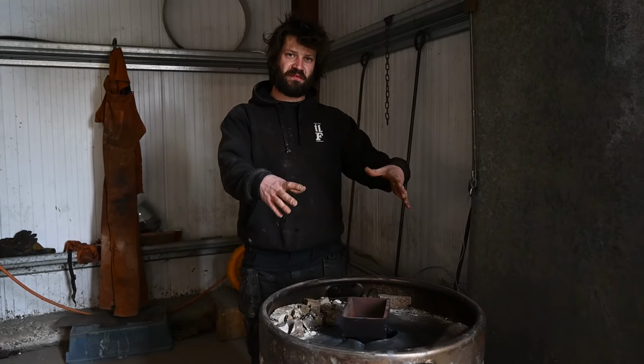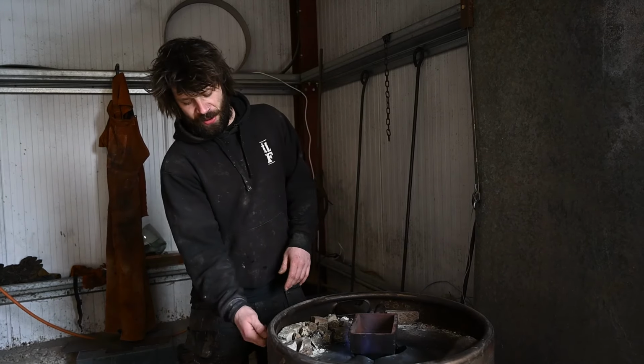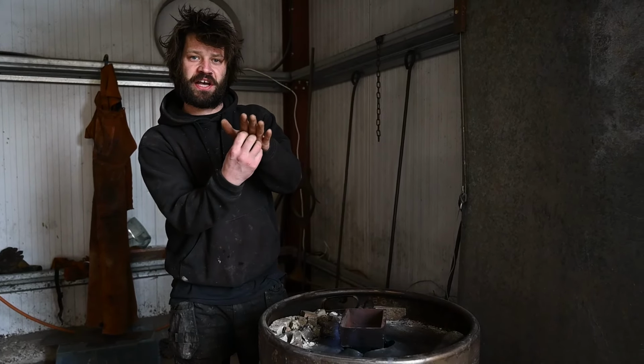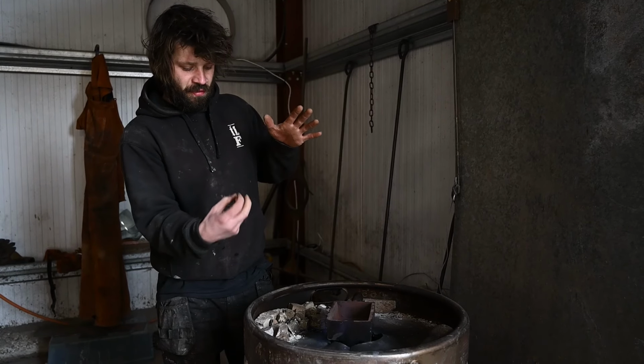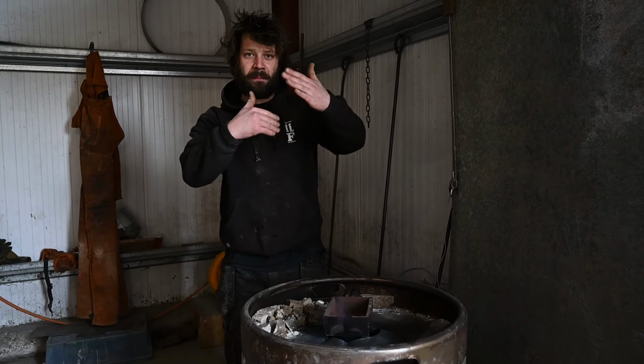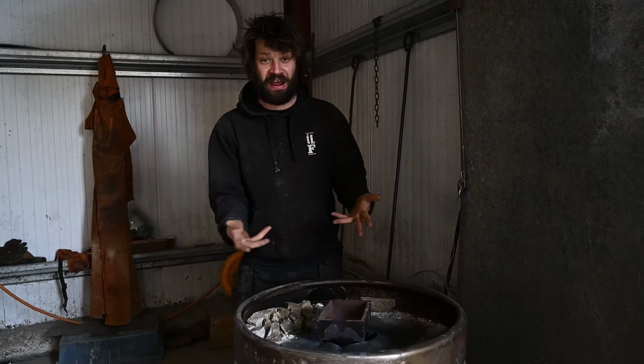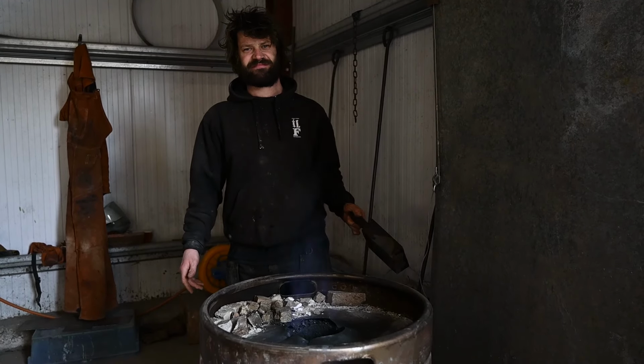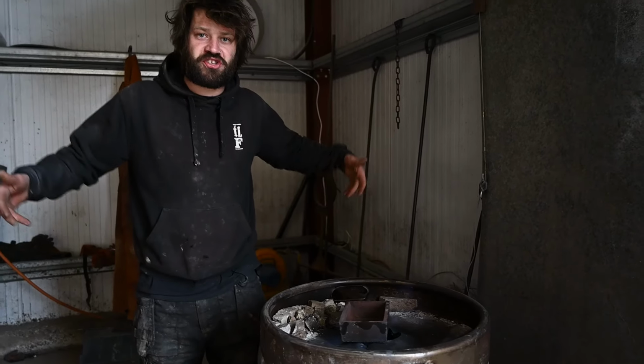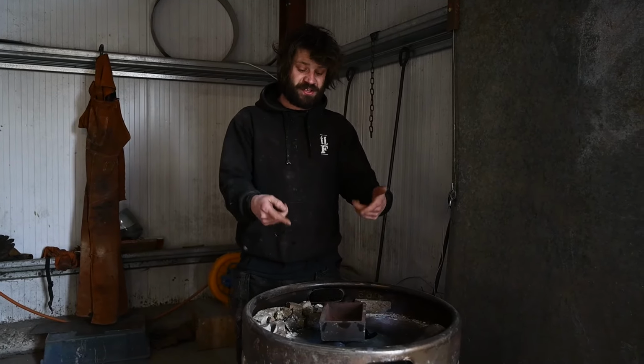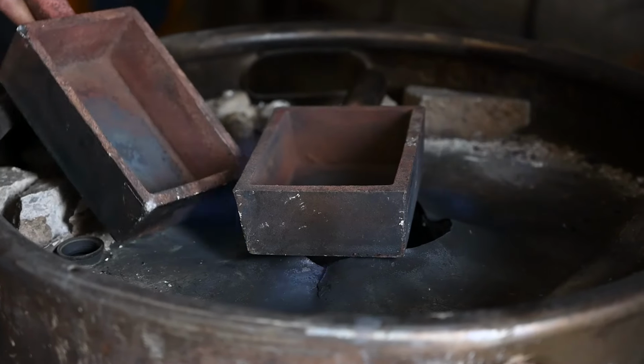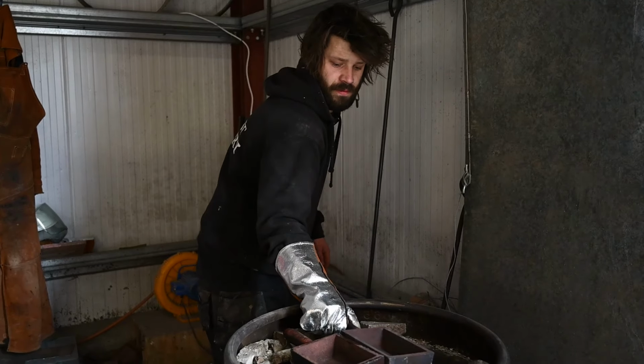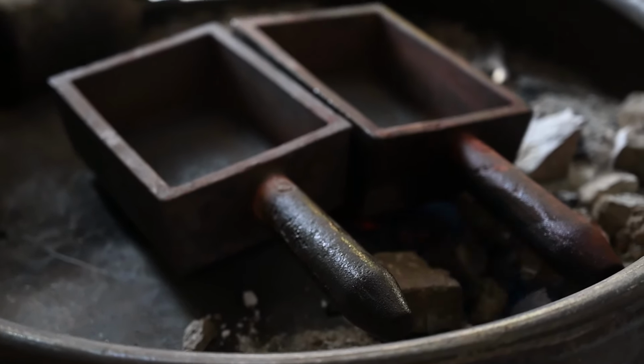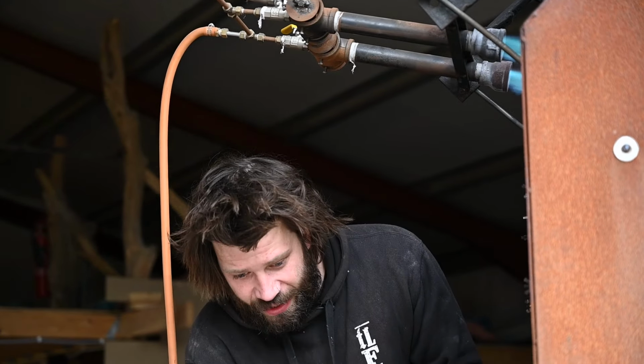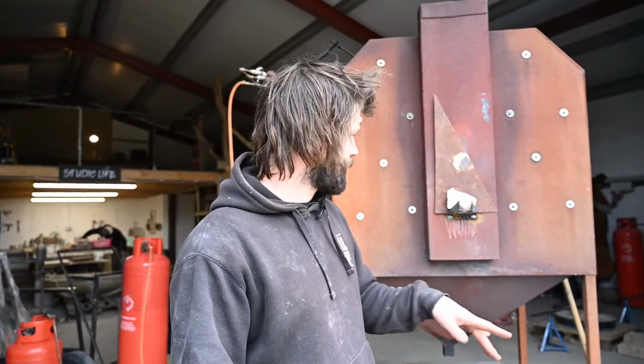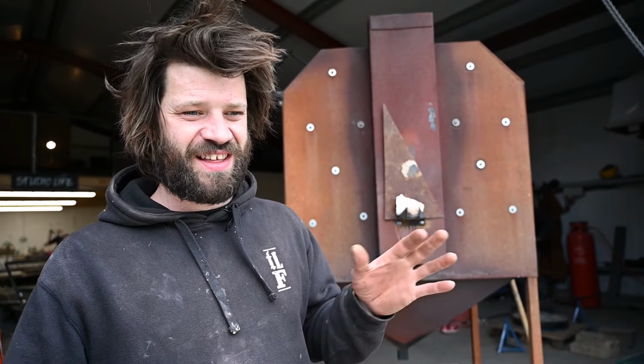This has got a massive hole in the furnace, and when I built this lid, I didn't key up the inside of the lid enough, so the refractory comes away from the lid. The vibrations of the refractory and the lid and the flame just create this horrible noise. So we block up the hole to stop the energy flowing through, and it also keeps the furnace nice and hot inside. I've just turned on the second burner now because it's actually really quite hot in there, just to give it a little bit of extra heat.